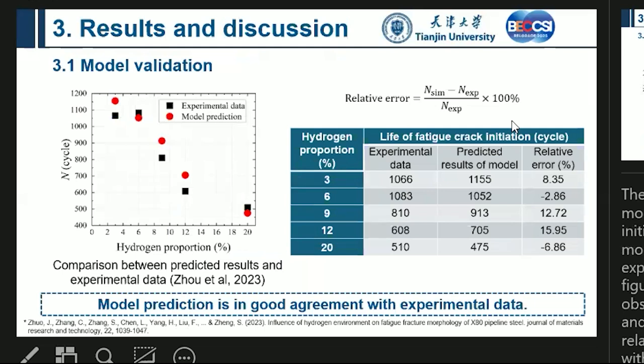Eventually, we take a look at the results. So the relative error between the model prediction and the experimental data. If you take a look at this table, the maximum relative error is only about 16 percent. So it looks like it's still good. So the model prediction is, in general, in good agreement with the experimental data.